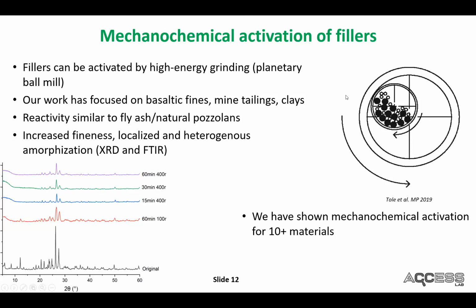Most studies in literature use what is known as a planetary ball mill - not your conventional ball mill. A conventional ball mill is just this, but a planetary ball mill is more like this - there's a counter rotation, which causes a lot of tumbling action, a lot of heat, etc. So pretty high energy. Typical ball mills rarely go over 100 RPM; these go up to 400, I've seen higher ones as well, so the RPMs are about 4 times higher.